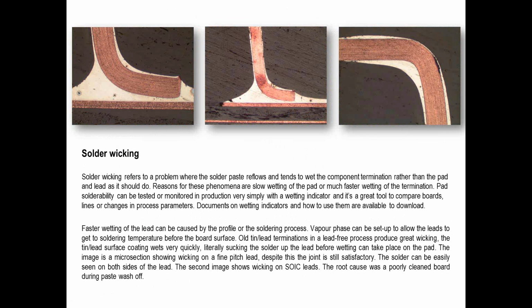Now, solder wicking can also be related to heating, it can be related to vapor phase reflow, and it can also be related to convection reflow with nitrogen. As an example, if you're running a product and you tended to see a lot of your paste volume, your solder volume, being sucked up the pins, sucked up the legs, as you see in these three examples, and you were running convection with nitrogen, all you need to do is reduce the quantity of nitrogen, i.e. dirty up your process. You'll save money on nitrogen costs, but you won't get the same speed of wetting, the same degree of wetting, so consequently you won't get this wetting away from the termination.